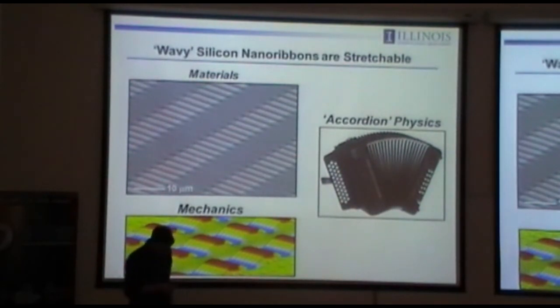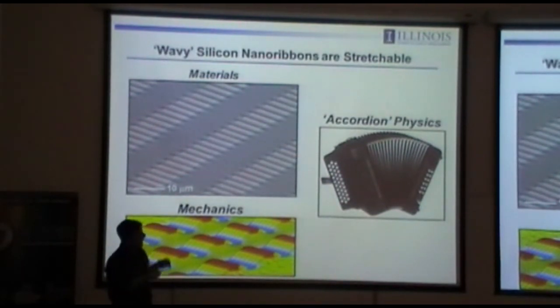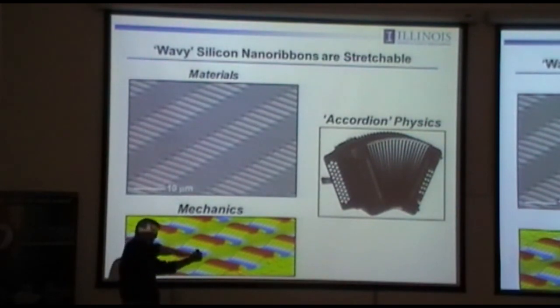Idea number two, and again, I won't get into the details, just try to give you a high level idea of this, is that if you want something to stretch, it goes beyond bending mechanics. So no matter how thin I get silicon, it will never stretch if I just focus on thickness. You need another different qualitative idea, and that is take this thin silicon, and you want an overall system that's ultimately stretchable, so you probably want to use a rubber substrate. That's in fact what we do. But not a rubber substrate just in its static state. You stretch it out a little bit. Then you use surface chemistry to allow you to chemically bond those silicon ribbons to the surface of a silicone rubber substrate in that pre-stretched state.